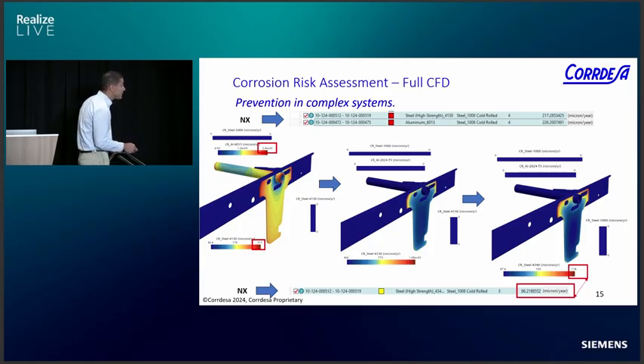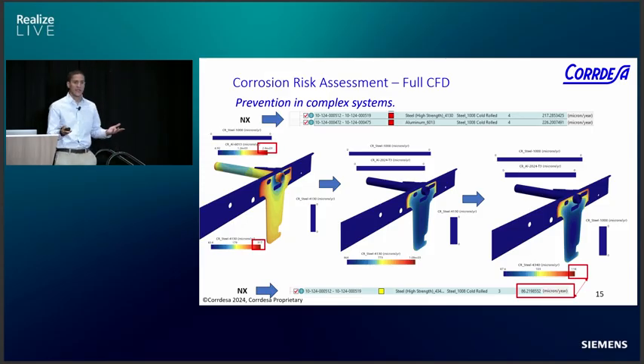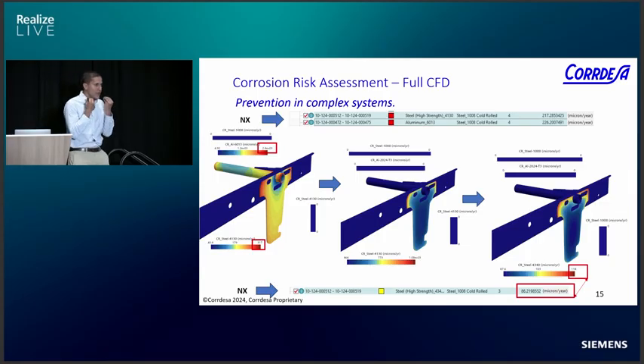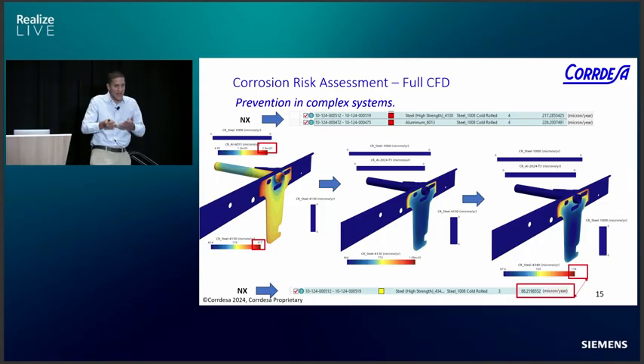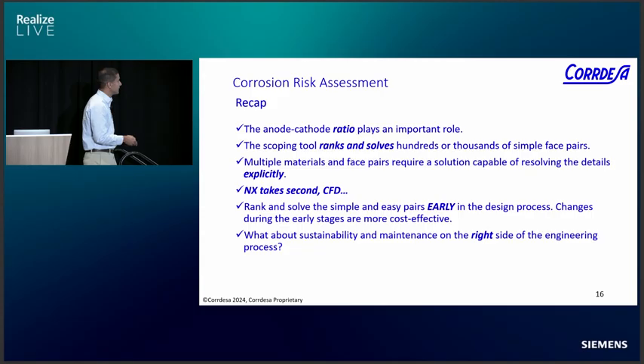And what we see here is that we reduce the corrosion rate of this component from 1,000 microns per year to 120 microns per year. If I do the same process in NX, changing from this material to this material, of course, NX only takes into consideration the interaction between these two. It reduces to 86, which is great. It's definitely great. The point I want to make here is that we have to use the right tool at the right point of the engineering project.